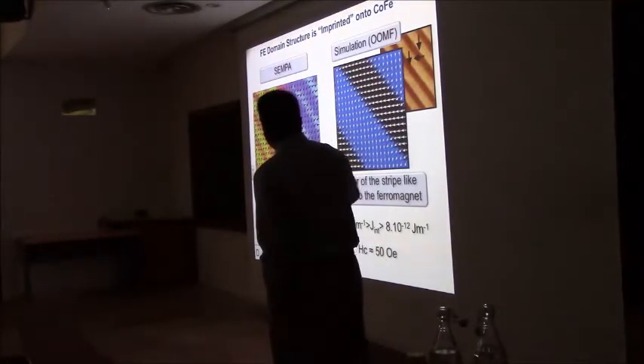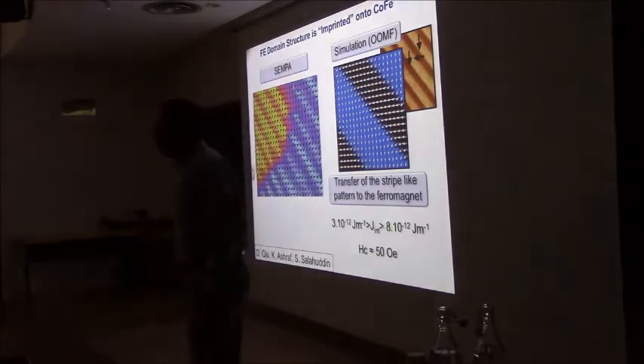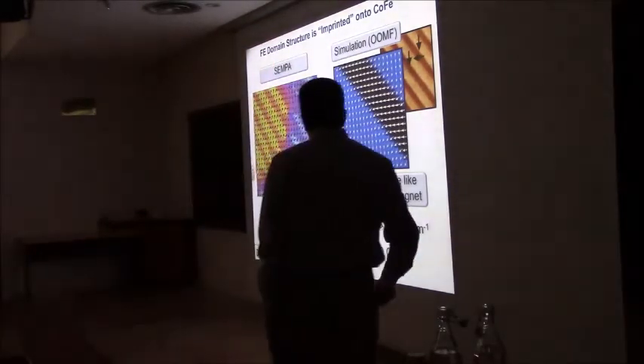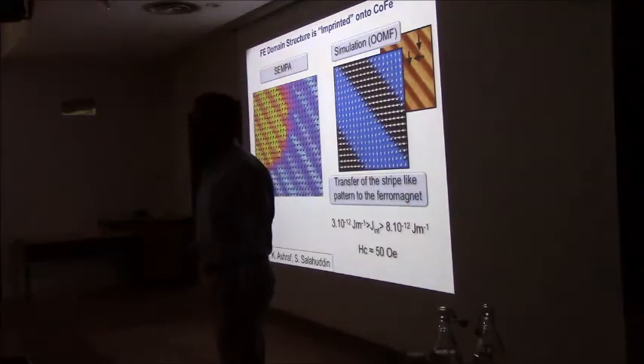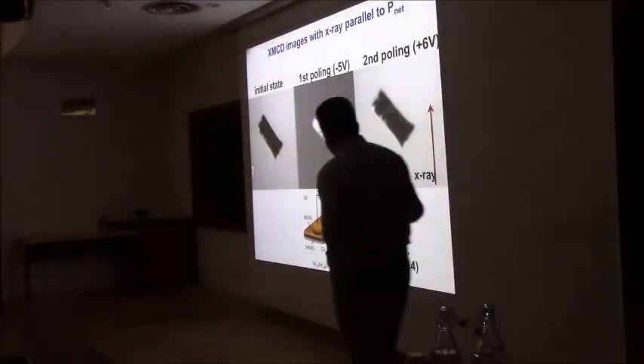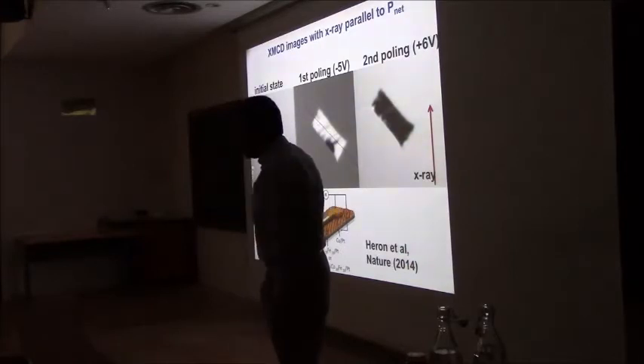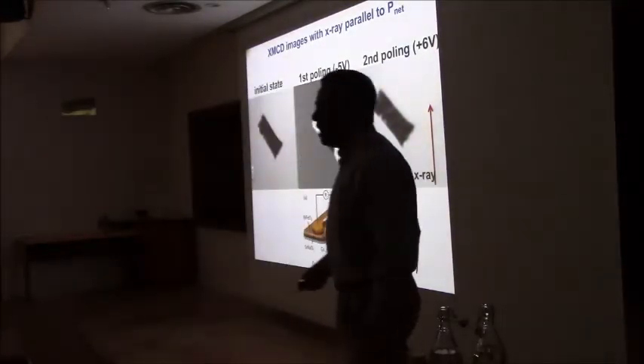So we've seen all of this already. You saw this picture. This is another way to image magnetic domains: scanning electron microscopy with polarization analysis, very similar to using X-rays to image the magnetization. You can indeed do vector mapping on a microscopic scale of what happens to the magnetic moment in the sample. Okay. The experiment that we did, which got published in this paper a few years ago, was a very difficult experiment because we had to repeat it 3-4 times, and getting beam time on synchrotrons is very difficult.